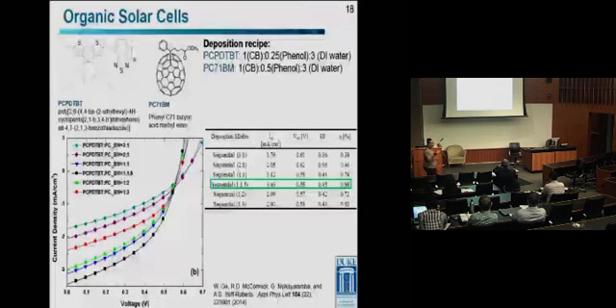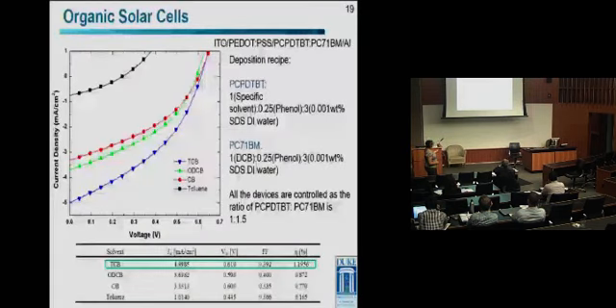Because you don't define composition in the same way that you do for solution-based deposition. And so we got something about 1 to 1.5 at 0.86% power conversion efficiency. If you'll notice, in this case, our primary solvent was chlorobenzene. So another study that we did was just to change the primary solvent. So we looked at trichlorobenzene, dichlorobenzene, and chlorobenzene with toluene.